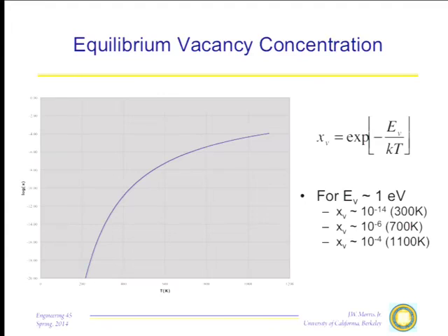And if you get the temperature even higher, the number of vacancies keeps going up, and the motion, the redistribution of species becomes much easier. What does that say? If you're going to move substitutional species around, you've got to have a good furnace. You've got to get up to good high temperature. And the reason is not really the mobility of the atoms. They're a little bit more mobile, but not a lot. The reason is the equilibrium fraction of vacancies.